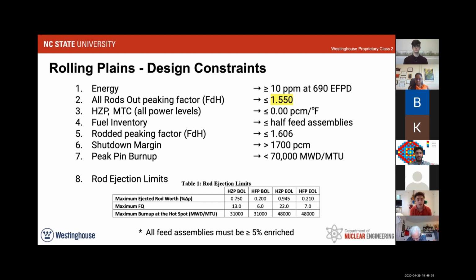We also had to have a hot zero power MTC at all powers had to be negative, and our fuel inventory. So we were tasked with using less than half feed assemblies of the core. So we can use half fresh assemblies and half previous burned assemblies. This is a challenge when going to extended cycle lengths because you really want as much fuel enrichment loaded into the core as you can to meet that cycle requirement. And so that was our limit, was less than half. Then we have our rodded peaking factor, FDH, less than or equal to 1.606. So that's with the control rods inserted to their rod insertion limits. And we also had shutdown margin greater than 1700 PCM.